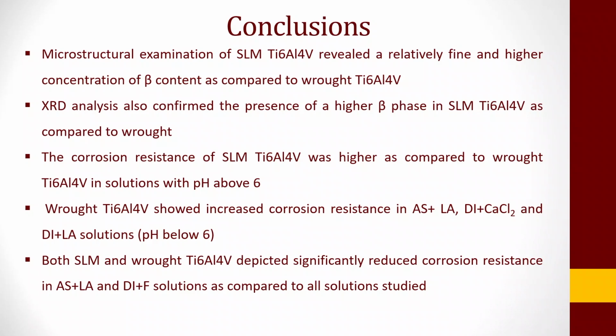So finally, to conclude, microstructural examination of selectively laser melted Ti-6-4 revealed a relatively fine and higher concentration of beta content as compared to the ROT Ti-6-4. Also, XRD analysis confirmed the presence of a higher beta phase in SLM Ti-6-4 as compared to ROT. Again, when we talk about corrosion resistance, we see that selective laser melted has a higher corrosion resistance as compared to the ROT, especially when the pH is above 6.